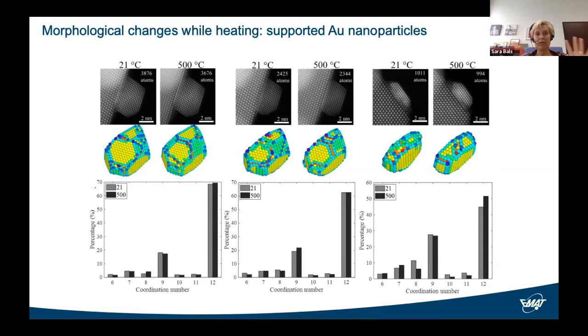On the left and in the middle, we have 2 different nanoparticles, but with sort of similar sizes. And what we see if we make a comparison between room temperature and high temperature is that the shape of the individual surface facet changes. But then if we look at the coordination numbers, which we also extracted, we cannot see a really significant difference. However, if we now look at the particle on the right, which is significantly smaller, we can see that we start with a flat particle. At higher temperature, it becomes more rounded. This can be seen in the 3D reconstruction and is also reflected by the increase of coordination number 12, which corresponds to the bulk atoms, indeed indicating a rounder shape.